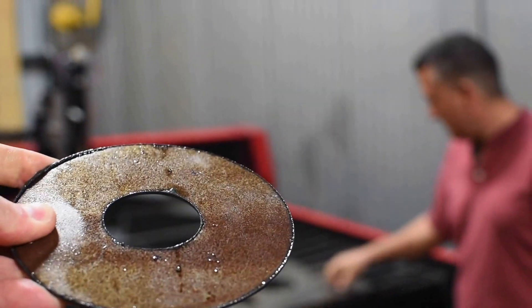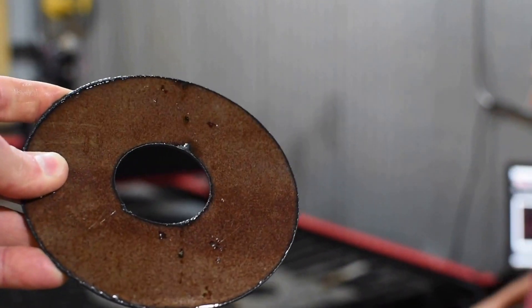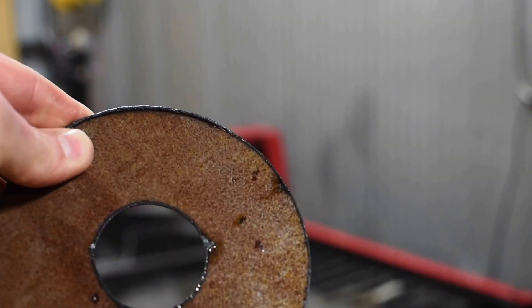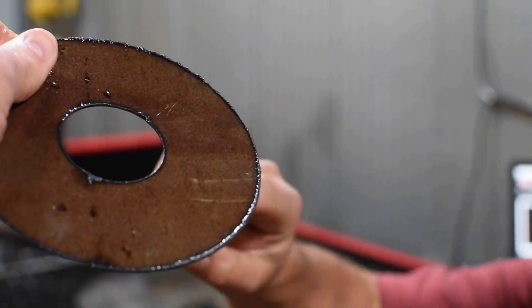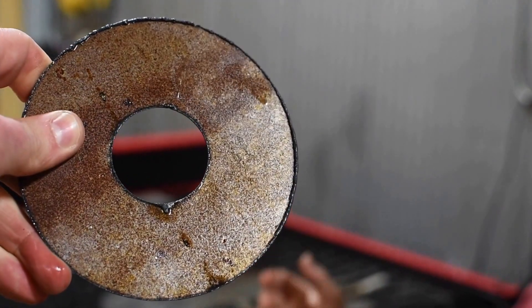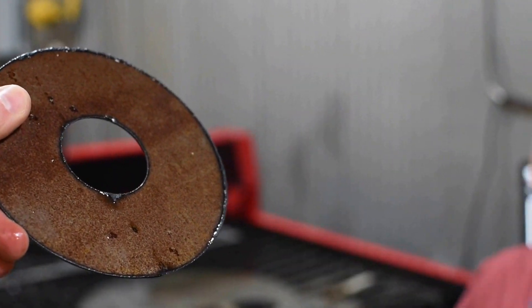It's still cool because of the water table. Not bad on slag. It's pretty decent on the slag actually. That's what I'm looking at. Yeah, actually the water level is a little low right now. So you can actually have a better, cleaner operation if I had the water level higher. And I did it at 100 inches per minute. If I do that slower, it'll be much cleaner.